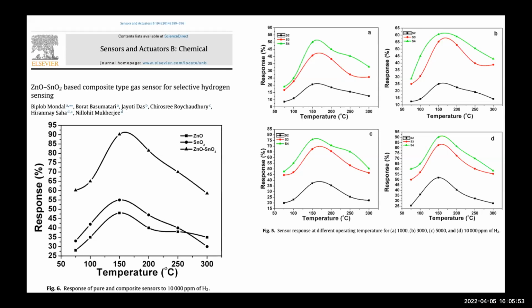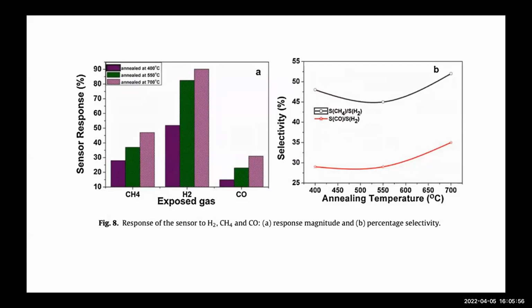So now in the next you can see the response for different gases. In order to investigate the selectivity, sensing studies of the composite sensor were performed with other gases like methane and carbon monoxide. It was seen clearly that the response of the sensor to hydrogen was highest among the other tested gases. The second graph shows the percentage selectivity of the sensor operated at 150 degrees Celsius to 10,000 ppm of each gas. It can be seen that the sensor is most selective to hydrogen.